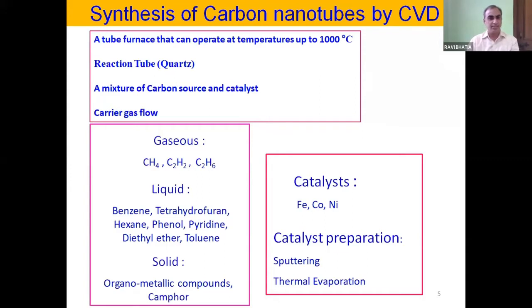Acetylene, methane, ethane, these are the gaseous counterparts for the production of carbon nanotubes. Benzene, tetrahydrofuran, hexane, phenol, all these organic materials have been used for the production of carbon nanotubes, and solid materials, organometallic compounds such as ferrocene, nickelocene, cobaltocene, and camphor. But in the case of organometallic compounds, you need not have another catalyst in the chamber. But while using camphor for the production of carbon nanotube, generally iron, cobalt, and nickel are used as catalyst.